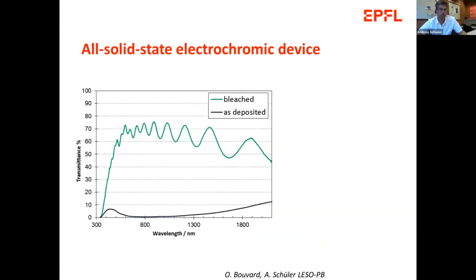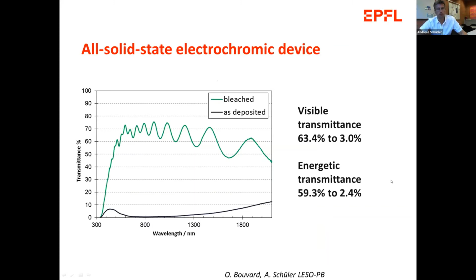And then we can make switching systems here. So this is a spectrum of transmission for the dark state, that is the solid line here, the black line, and for the clear state, that is the green line here. And you can calculate the visible transmittance. This device switches from 63 to 3% in visible transmittance, and the energetic transmittance switches from 59% to about 2%.